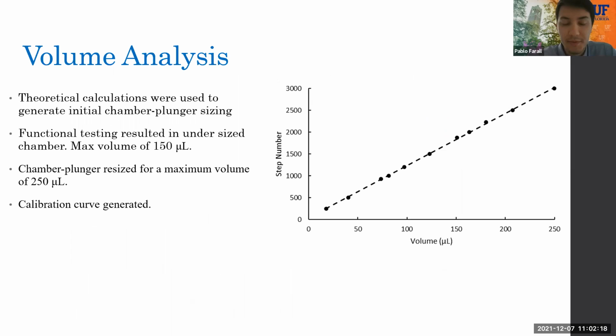So one of the main objectives from our design was to make sure that we could have a highly accurate pipette. The volume analysis started before we even manufactured a single part. In order to size the plunger and chamber, initial volume calculations were made using the size of the inner chamber and the volume geometry. Initial sizing resulted in an undersized system with a maximum volume of 150 microliters, and we think this is the result of an undersized tolerance in the chamber. We then redesigned the plunger and chamber for a maximum volume of 250 microliters, adding a 50 microliter buffer.